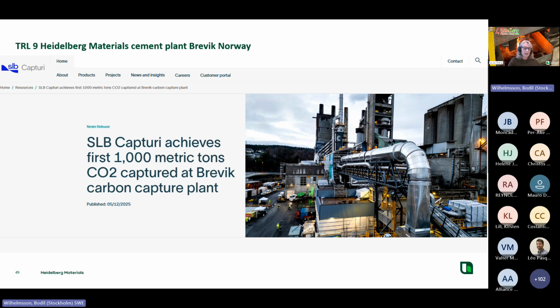And this is of course good, but is there something we can do even better in the future to decrease this energy consumption? As I was talking about, it increased, but here in Brevik, they capture 50% of all the CO2 in the flue gas, and that is because the waste heat from the plant is able to be used. So the energy for this captured CO2 is not as high as 5.5. That is a theoretical value when you don't have any waste energy. So this is better.